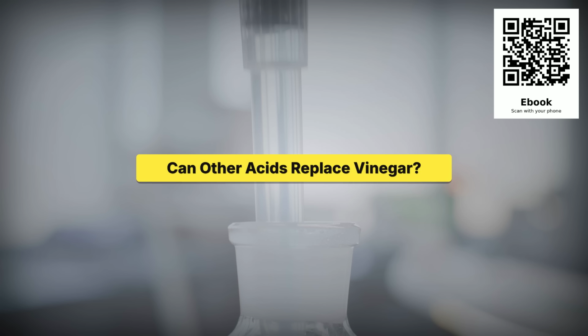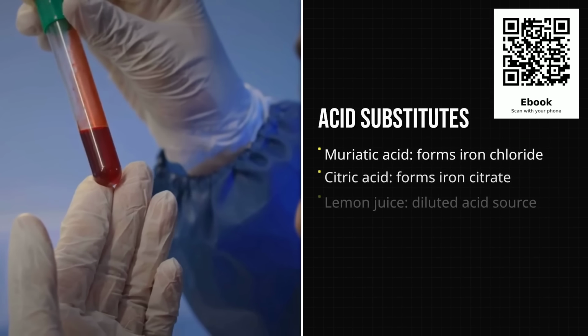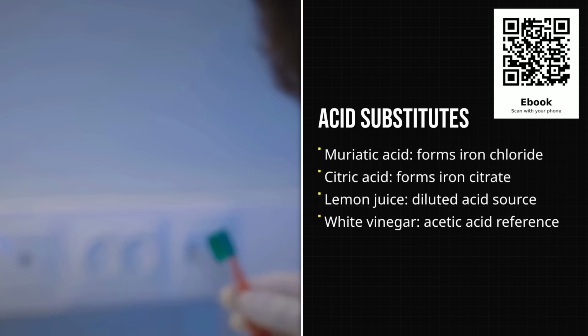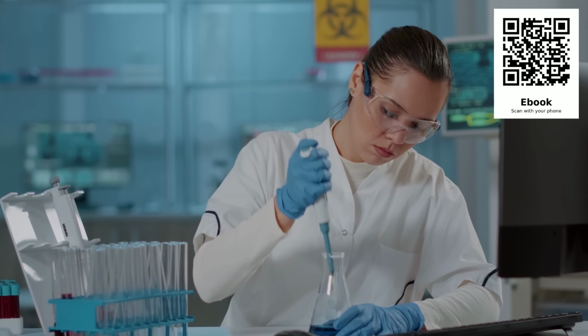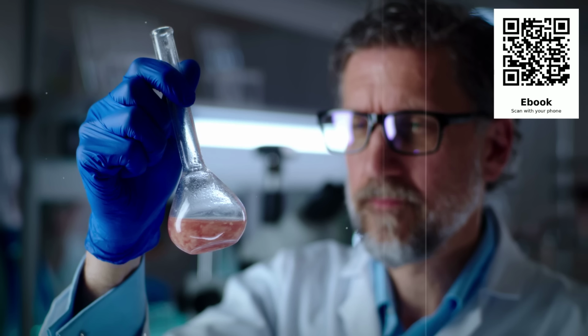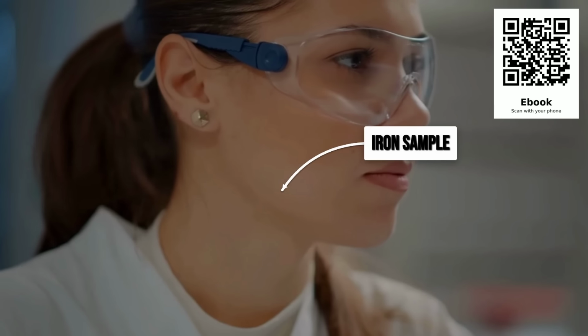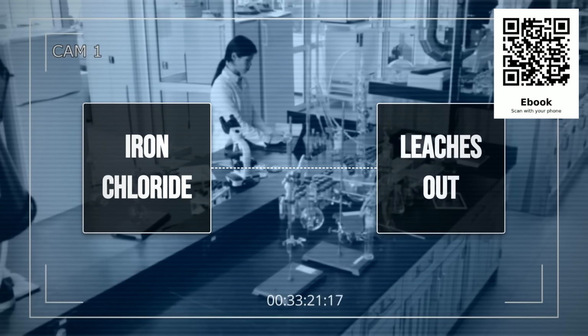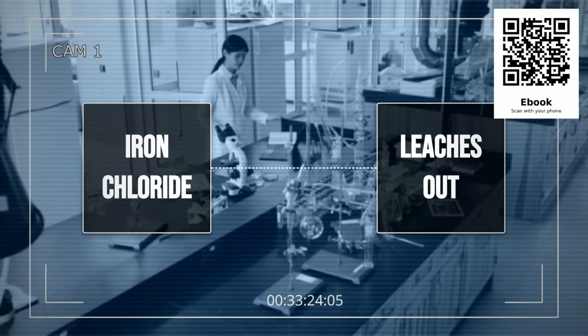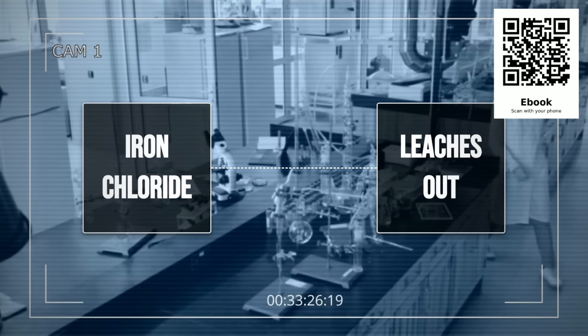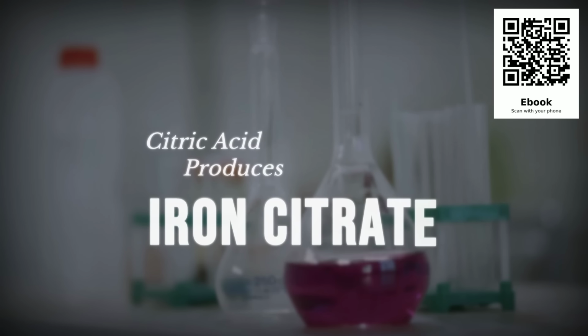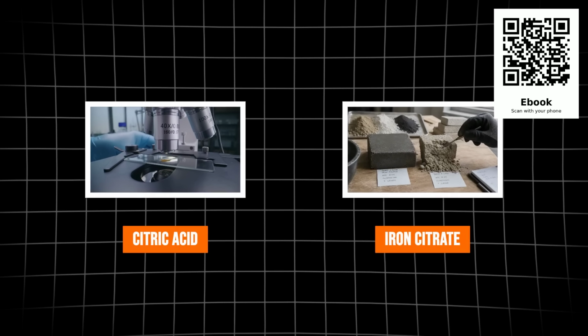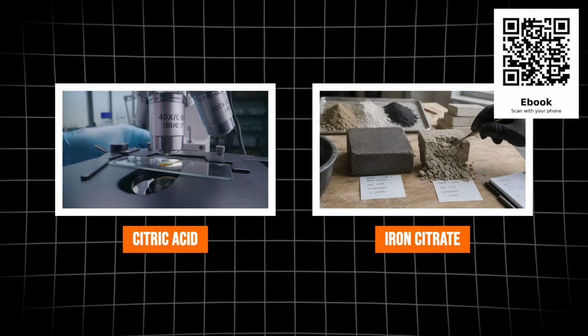Now, can you substitute other acids for the vinegar? People have asked me about muriatic acid, citric acid, and even lemon juice. The answer is that acetic acid, which is what vinegar is, has a particular molecular structure that allows it to dissolve iron slowly and produce a stable acetate that will hang around long enough to react with the lime and sand. Muriatic acid dissolves iron too fast and produces iron chloride, which is water-soluble and will leach out of your mixture instead of bonding into the crystal lattice. Citric acid works, but it produces iron citrate, which is less stable and gives you a weaker finished product.